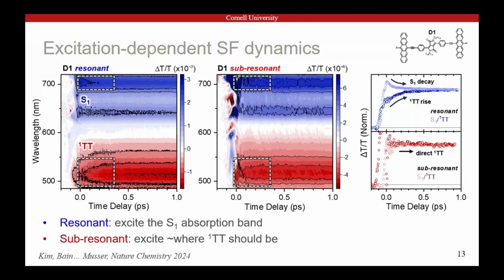So now if we come in with our red pulse below the singlet absorption energy, we can see exactly the same triplet pair state signature that's present on longer time scales. But on the earliest times, there's no sign of this initial singlet decay. There's no sign that we started in the singlet state. The only thing we can see with 10 femtosecond resolution is the triplet pair. So we go from a regime with clear dynamics to a regime with no dynamics of conversion at all. Looks like we're directly photoexciting the TT state.